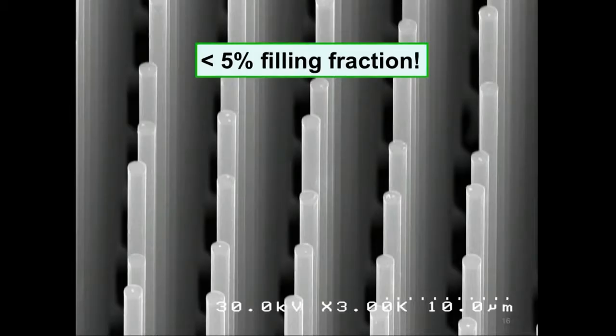Well, let's look at the optical properties. When we first did this, we knew that we would have one optical problem. At the appropriate pitch, with 2 micron diameter rods whose diameter is matched to the 1 micron diffusion length so we can collect all the carriers sideways, on a 7 micron pitch, which happens to be where we have the minimum reflection, because on this scale length, when the rods get too close, they look like a bulk material, and they reflect like silicon would reflect with a high index of refraction. When they're too sparse, then light just goes right through. Even then, when you look top down, that only fills 4% of the incident optical plane. So, according to the laws of optics, we should only get 4% total efficiency at best of light absorption, because 96% of the light should go right through.